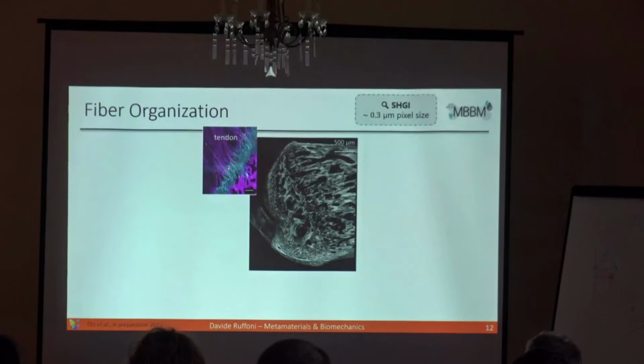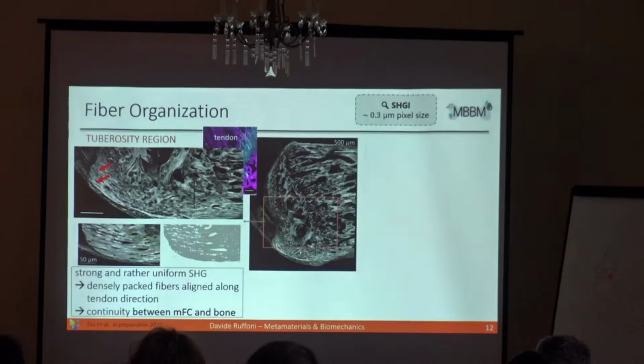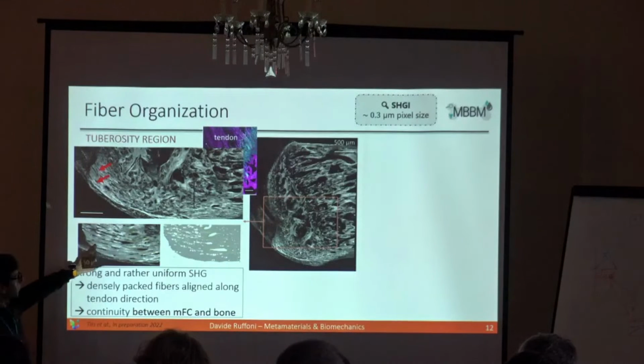Now, you remember in the introduction I said that people have concentrated on looking at what is happening more from the tendon side. So there is this beautiful work that analyzed fibers of tendon when reaching into bone. What we did now is visualize the orientation of fibers inside bone. For this, we use a technique which is called second harmonic generation microscopy. We excite bone with laser light, and we look at the second harmonics which are coming out from the tissue. And what we see at the interface, where tendon is inserting into bone, here is tendon and here is fibrocartilage, is that the second harmonic signal is very uniform, very strong, and this suggests very aligned fibers.